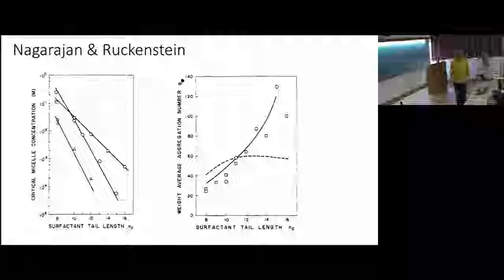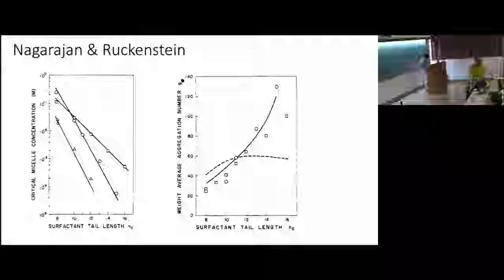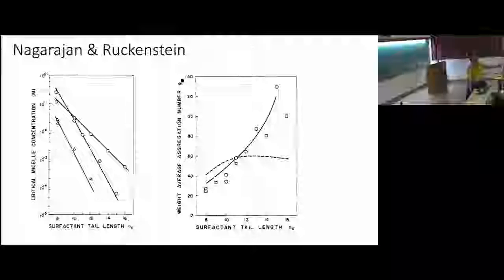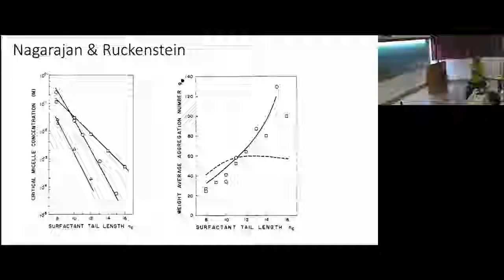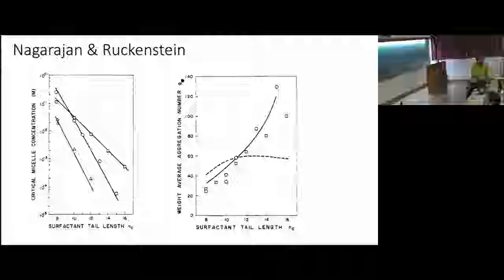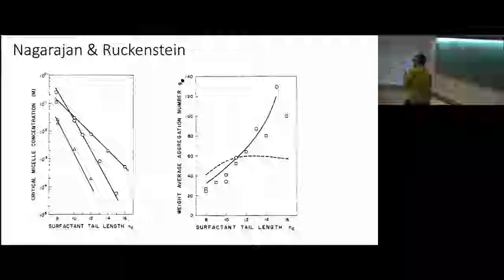So here's the final proof — this actually works. These are the two guys I told you about, and these are those three classes of compounds. The surfactant tail length is being changed, and the range goes from 8 to 16, which is the sweet spot. If you make it too long it becomes a solid and the conformational entropy of the tail no longer matters; too short, it becomes rigid. They think the persistence length — the length over width at which the chain behaves like a rod — is about 6 carbons. Larger than 6 means it's really a baby polymer chain.